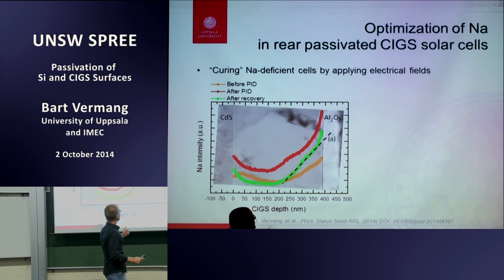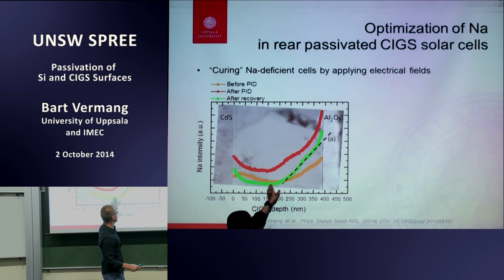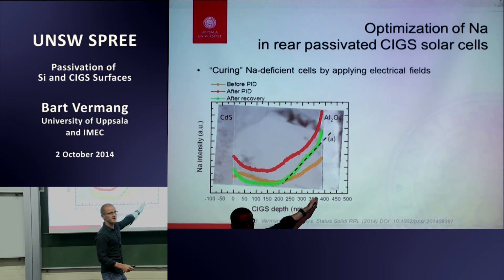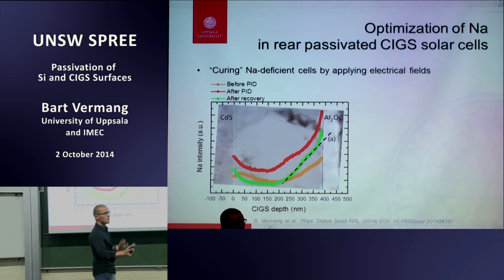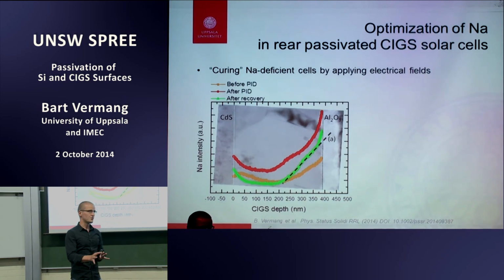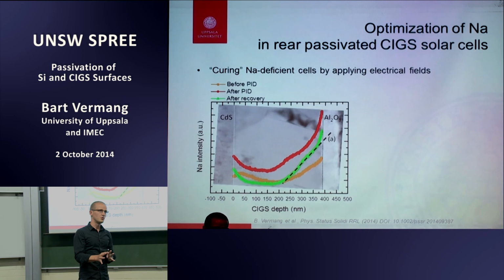However, it's true you have more at the interface, because when you take it out, again, the aluminum oxide is blocking. It's a barrier. And we don't completely understand what's going on there. But the passivation definitely is coming from the aluminum oxide only. It might have an impact from the sodium as well for the passivation, but aluminum oxide only works as well.